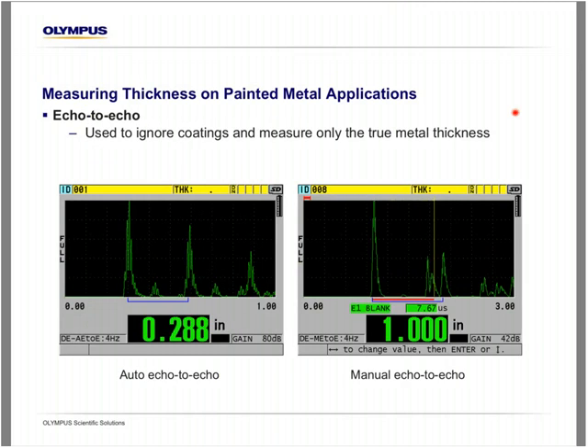So the next application is measuring thickness on painted metals. We actually have 2 solutions. We have either echo to echo or through coat. So echo to echo has been used for many, many years to ignore coatings and just measure the true metal thickness. And the way we do that is to measure the time of flight between successive backwall echoes. So when you do echo to echo, you have the option to choose either automatic or manual.